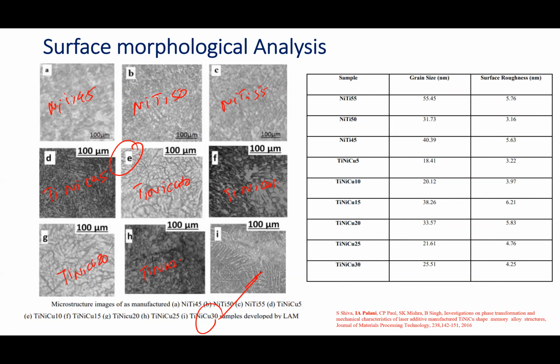And as and when we increase to TiNiCu10, the grains gradually get bigger than in TiNiCu5, and mild deposition of precipitate-like structures is visible, which might be due to improper powder melting. And TiNiCu15 has very large grains compared to the other samples, and the presence of pores at isolated locations is observed. So this might be due to improper melting of the powder particles in the laser additive manufactured structures.